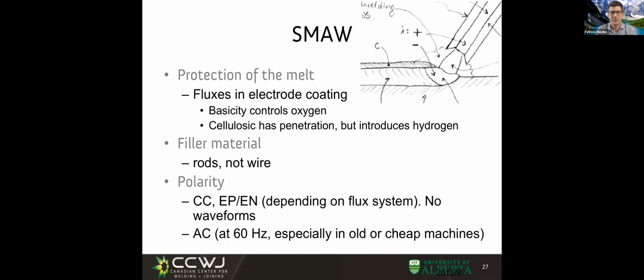And these electrodes can cause us headaches because this hydrogen, when we weld steel, can result in cracking. And if you remember when we talked about the names of the passes, for example in pipeline, we said we have a root pass, a hot pass, filler passes, cap passes. The root pass is typically done with this cellulosic electrode that can have hydrogen. Then we follow up the hot pass with an electrode that looks more or less like this, but it's low hydrogen and helps us heat the hydrogen away, right? Very interesting.